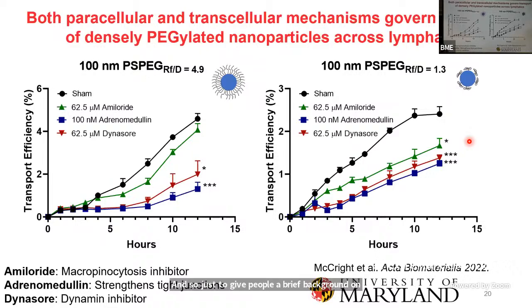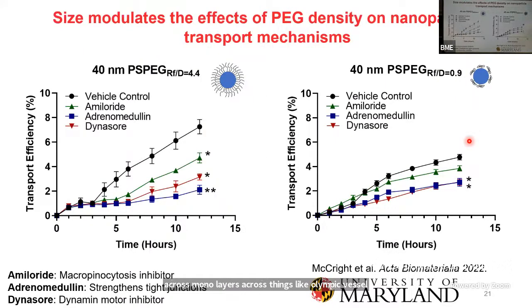Now we were curious, is this all the same depending on the size as well? So we would expect that probably, yeah, you're going to have similar mechanisms, but what we found was actually really interesting. So you can definitely still see the same effect in terms of macropinocytosis and paracellular transport. So you see a reduction in those, but with amiloride, our macropinocytosis inhibitor, we actually found that when you have a densely pegylated 40 nanometer particle, now you also see a reduction in transport when you inhibit macropinocytosis. And you don't see as much of a reduction. There's maybe a little bit, and some of these individual time points are significantly different, but it's not nearly as drastic as with the 100 nanometer particles of those less densely pegylated particles.